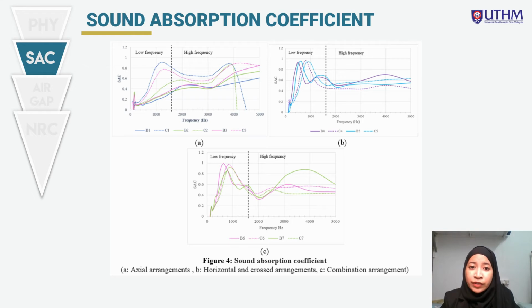Next, we can see in figure 4b, if we compare the cross and horizontal arrangements, the cross arrangement demonstrated higher SAC values compared to the sample with horizontal arrangement throughout the frequency. Lastly, for the combination arrangement, it is best to conclude that samples made up of a smaller Stokes diameter give an optimum sound absorption property, especially at higher frequency range, compared to samples made up of a bigger Stokes diameter.